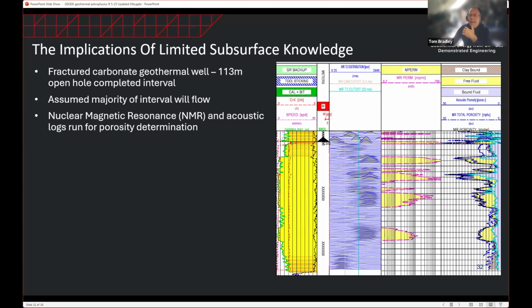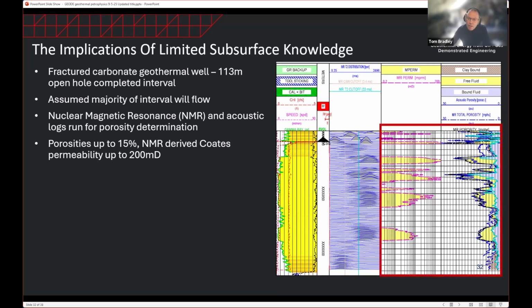And straight away you can see here, just looking at this porosity distribution, we've not got that much movable porosity. In fact, if we actually did some computations on the permeability here, we've seen porosity to 15%, and in some intervals, permeability is up to about 200 millidarcies.